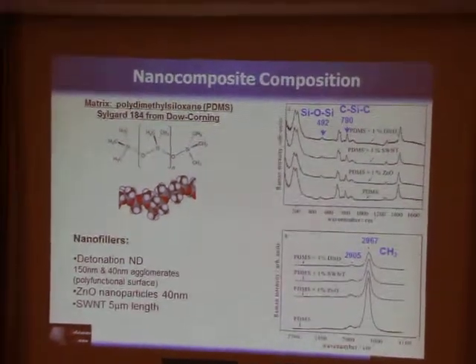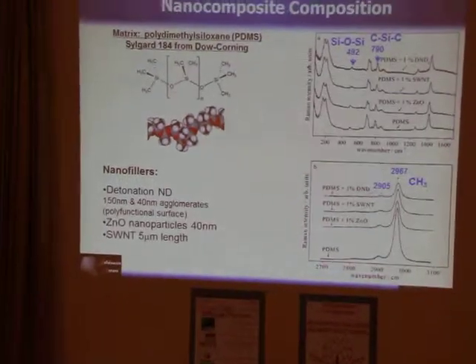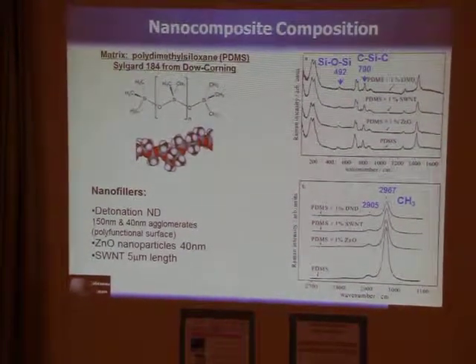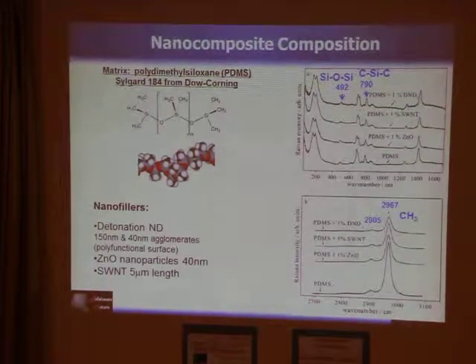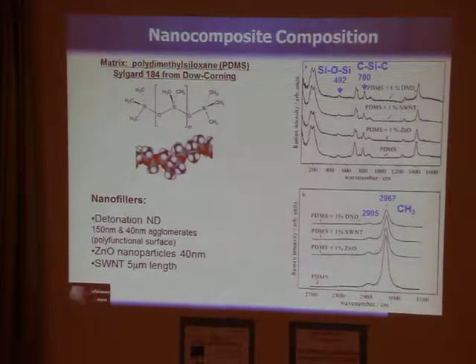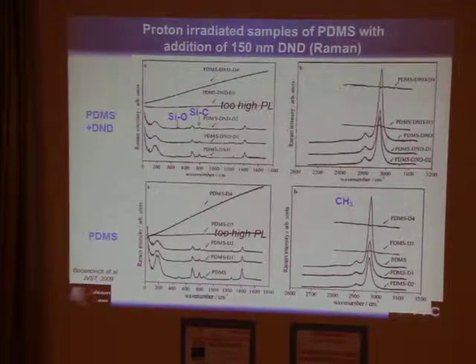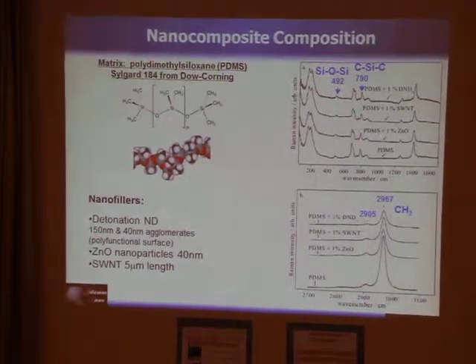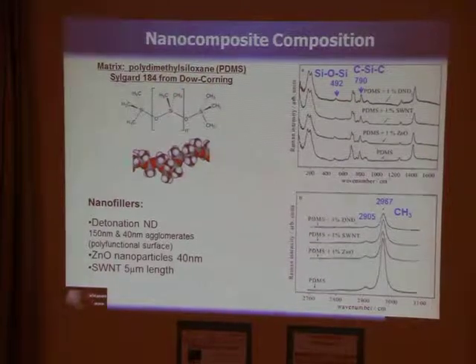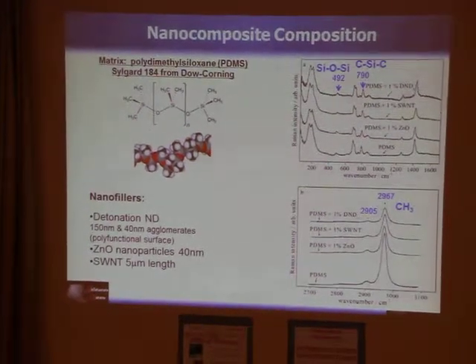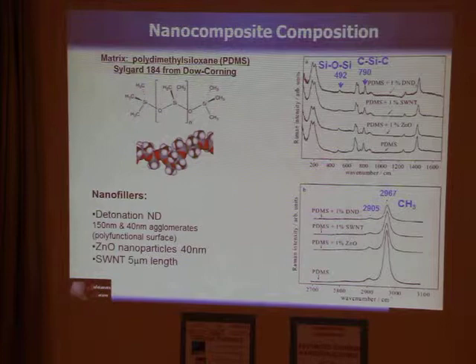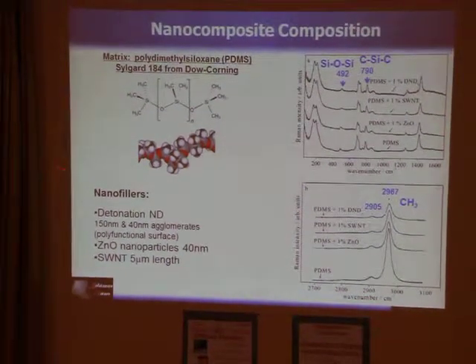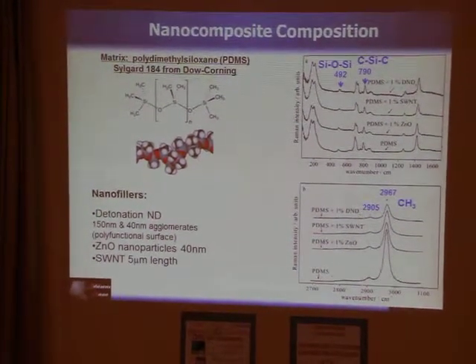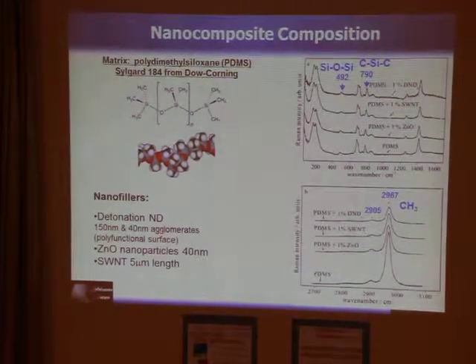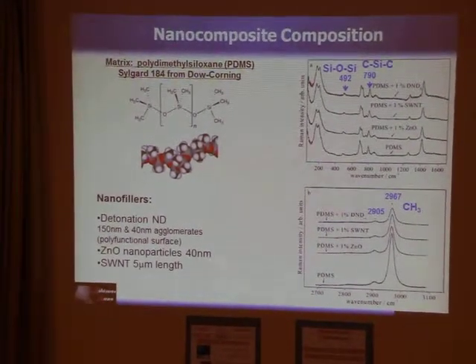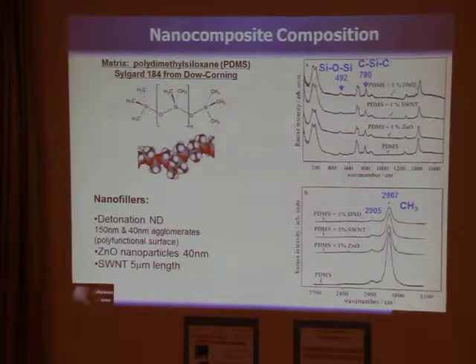Siloxanes are used as paints in spacecraft, so that was a motivation to choose this type of polymer matrix. It consists of a silicon-oxygen backbone and CH3 side chains. As nanofillers, we used detonation nanodiamond with 150 nanometer and 40 nanometer agglomerate sizes with a polyfunctional surface.